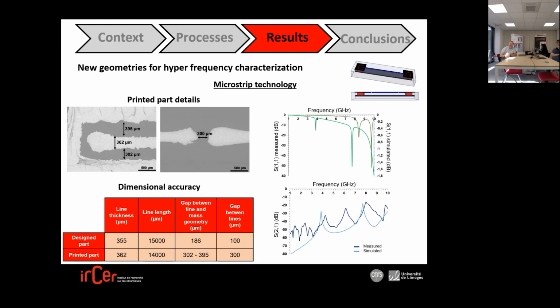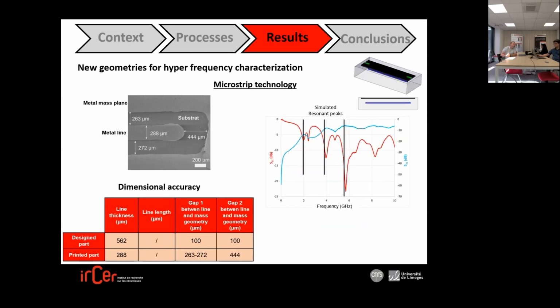On the right of the slide, you can see the frequency response of the printed component. There is a little difference between the simulated signal and the measured one, even for the S11 signal and the S21 signal, but in each case, we can see the two resonance peaks that appear not exactly at the same frequency as in the simulation, but this can be explained by the difference of printed geometries.